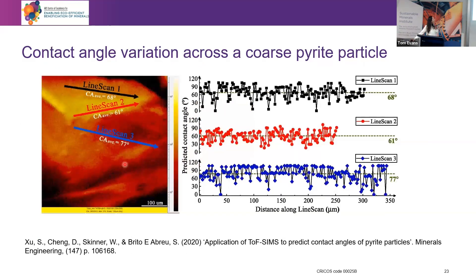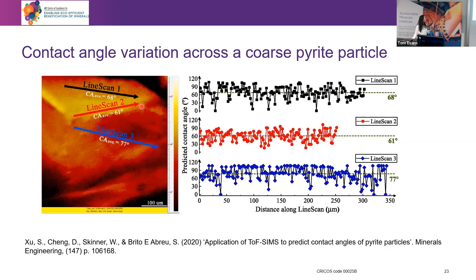We could also follow this procedure on a different system — in this case for a pyrite particle — and determine the hydrophobicity on different faces of the particle. What was very interesting to see was that the top face has an average contact angle of 68°, the side face 77°, but along the edge the lowest at 61°. This is a very interesting result because we know that edges are more reactive — the bonds are broken, they are more prone to oxidation — and it was very interesting to actually observe that on a chemical perspective.